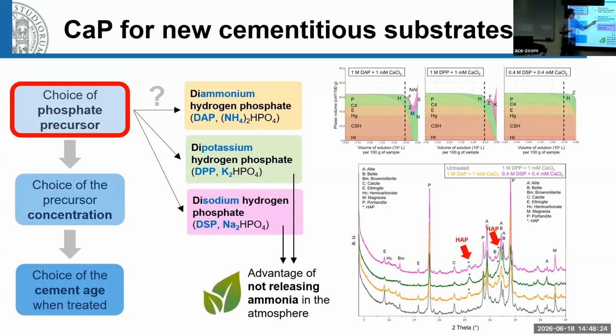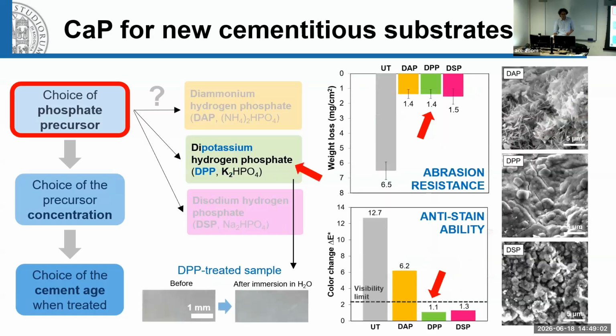The trade-off is that in this case, there are cations, sodium and potassium, that remain in the substrate, which in the case of stone is something that for sure you don't want. In the case of cement, because potassium and sodium are already present in the substrates, maybe this can be dealt with. So with some colleagues from Switzerland, we performed some thermodynamic modeling to predict what phases would form by using these 3 different precursors, and then we performed some experiments to check the formation of hydroxyapatite, and as you can see there, in all cases, hydroxyapatite was formed.